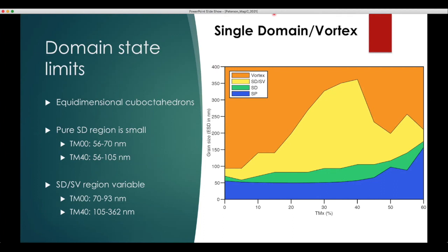I think this really highlights that there is quite a lot that we don't know, and that we've built a lot of our understanding around Néel theory and single domain theory, and that has served us well for a reasonable amount of time. But there's a realization that the vast majority of our recorders are not uniformly magnetized grains. They're in much more complicated domain structures, and they're not necessarily all pure magnetite. This titanomagnetite series is quite a substantial contributor to magnetic remanences. And so understanding and unraveling what some of this stuff means in a paleomagnetic context is something that really needs to be done.